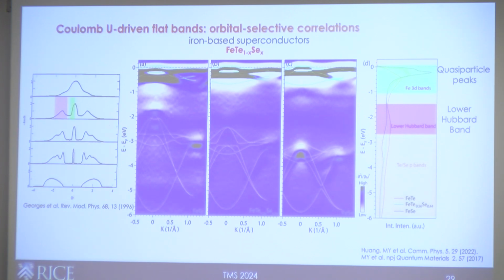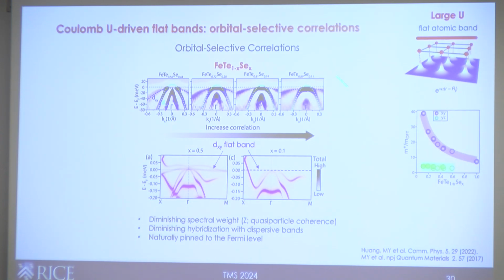And what's interesting about this system is that the iron-based superconductors are multi-orbital systems. They have more than one band, more than one orbital. So really interesting stuff happens near the Fermi level. I'm going to take the next couple of slides by zooming in very close to the Fermi level. So this is 1 eV, this is 100 millivolts, and this is what happens in that region. These are cuts taken on iron tellurium selenium. You can vary the amount of selenium versus tellurium. That's a tuning knob in this family. It's isovalent. But what you actually see is something interesting.